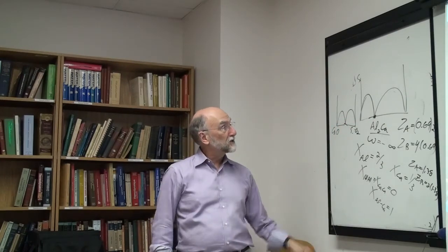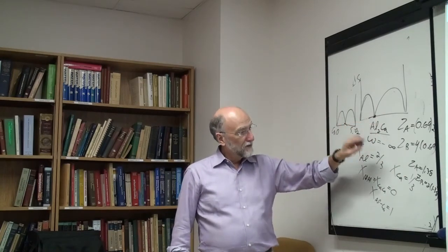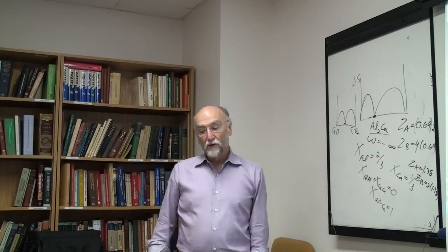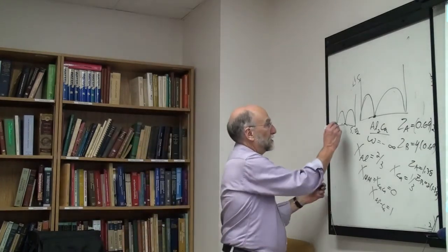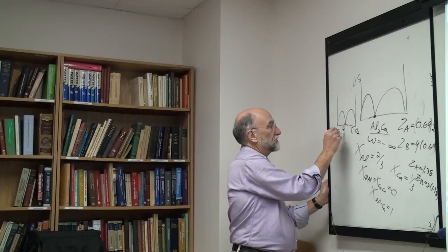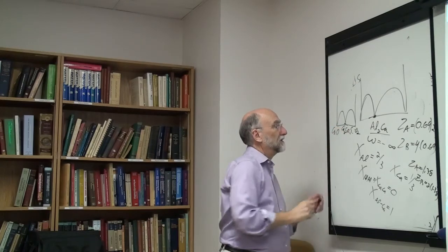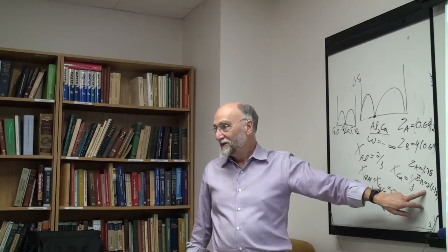Okay, but you see the idea here is I'm simply putting it back into the expression and finding what values of ZA and ZB will shift this over but still keep it 0. So one's got to be a bit less than 2, the other's got to be a bit greater than 2, and that fits it in. So if you look in the FactSage database for, say, calcium-silica, the minimum here is at Ca2Si, or whatever. And you'll find that the Z of calcium oxide is 1.38, and the Z of silica is 2 times 1.38. And that's the reason.